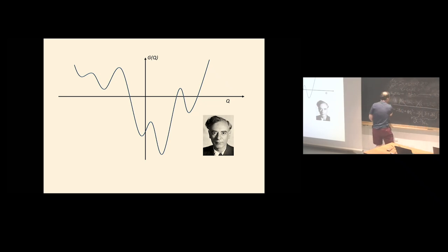Now let's look at the other version of events, which is the low temperature phase, where Q squared is minus B over 2D. So now we have low temperature. Q squared is equal to minus B over 2D. Substitute that in, we get B plus 6D, so this is minus, I'm putting the minus in already, 6D times Q squared, which is B over 2D. D's cancel, that's the magic. That goes to 3, and we're left with B minus 3B must be greater than 0. Minus 2B must be greater than 0. B must be less than 0.